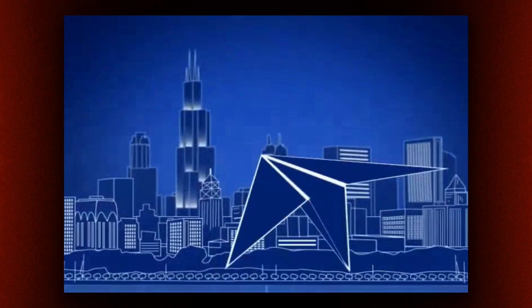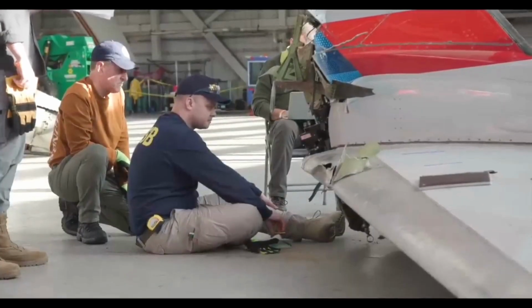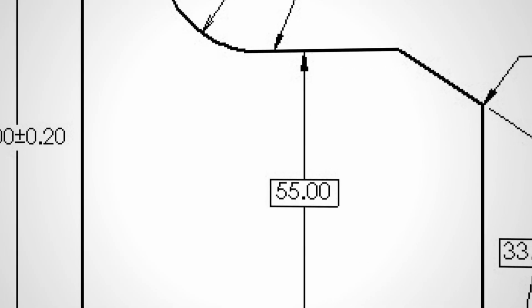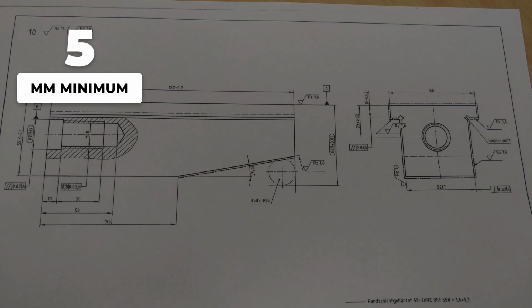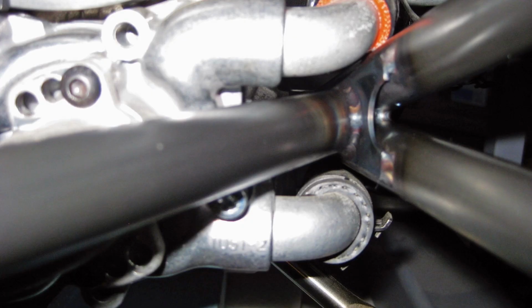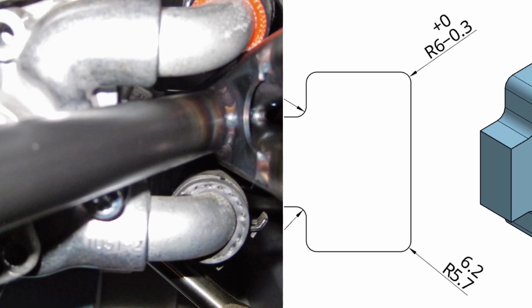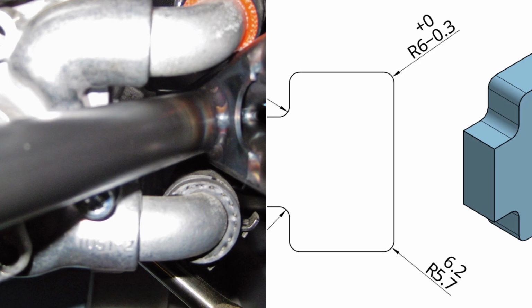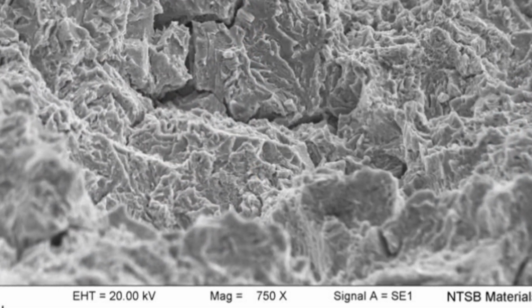An engineering drawing pulled from Boeing's digital archive overlaid perfectly with the lab's CT scan. The deviation was not theoretical. It was etched in metal, right at the crack's origin. A copy of the original blueprint, marked Revision D, specified a minimum tolerance for the fillet, no less than 5.0 millimeters at the critical interface. The failed fitting fell outside that window, its radius pinched and uneven. Photographs from the lab, annotated in red, highlighted the mismatch.